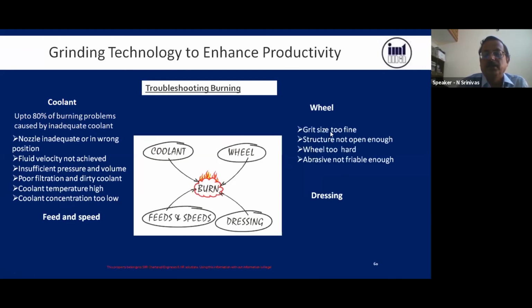So this is connected with coolant, and also the wheel. For example, grit size too fine. Then what happens? It will not take the cut at all. More heat is generated, and you will get a burning mark. Structure not open enough. An open structure wheel should be there. And wheel too hard. It's acting very hard. Hardness. Abrasive not friable enough. That is the type of abrasive you are using. So this is connected to the wheel.